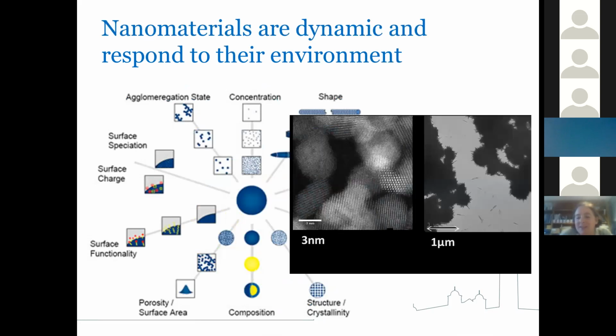Just as an example of that, these were cerium dioxide nanoparticles. They started off as 3 nanometers, so this is very high resolution and you can see the crystal structure in them. But when they were incubated over time in a soil pore water, so water extracted from soil that had phosphorus in it, they changed very, very dramatically, both in size. So they went from 3 nanometers to around a micron, 1,000 nanometers, but also they had these spikes growing out of them, so they became urchin shaped. And obviously the toxicity and the uptake of these two different entities will be hugely different.